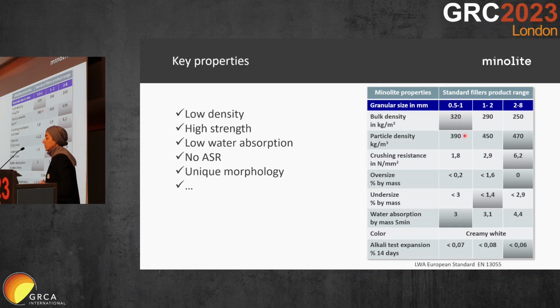These are some key properties of Minolite. If you look at the bulk density of different fraction sizes, you can see that, for example, for 0.5 to 1, the bulk density is 320 kilograms per cubic meter, and as the particles are getting larger, the density is decreasing. And if you look at the crushing resistance, it is a very interesting result here, because we expect that when the size of particles increases, the crushing resistance decreases, but it's opposite in Minolite, because we believe that this is because of the special formulation of the coating of particles.